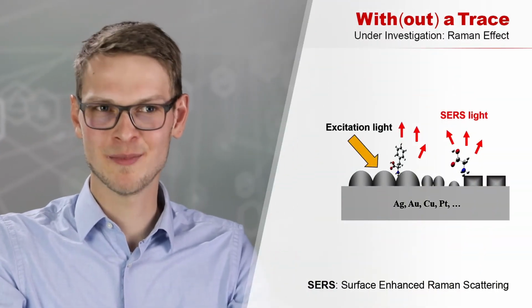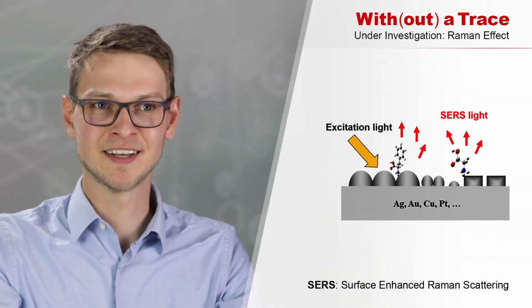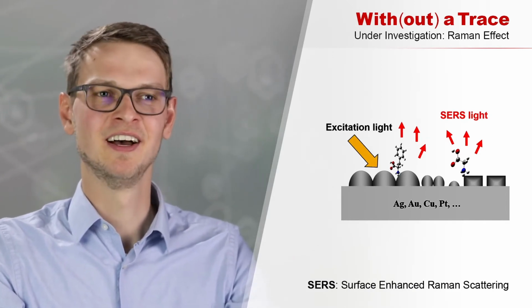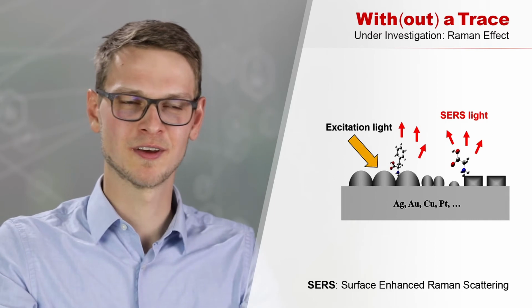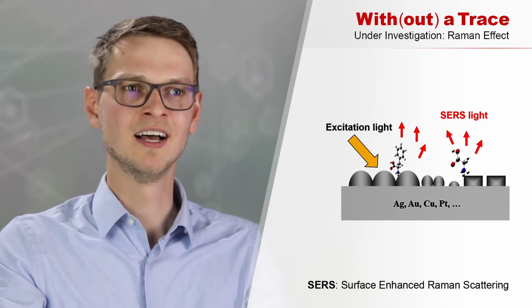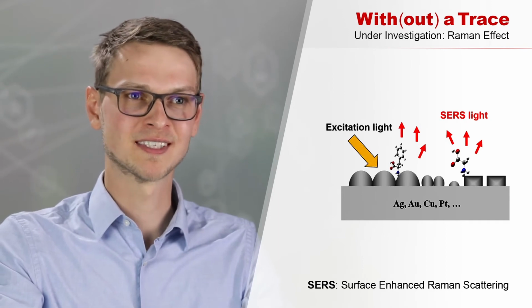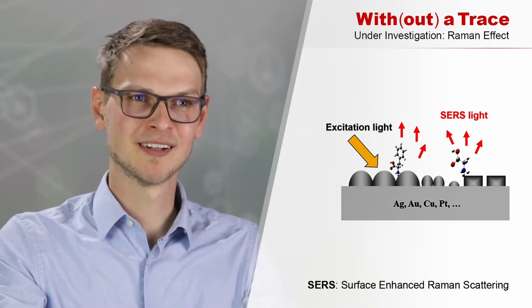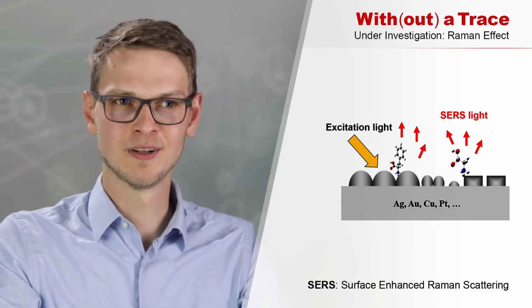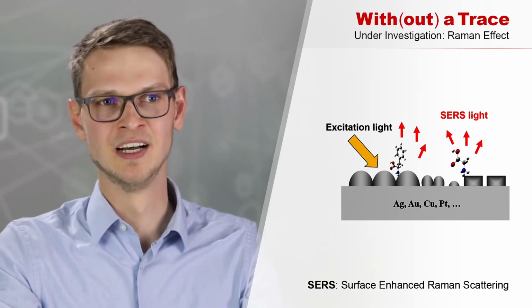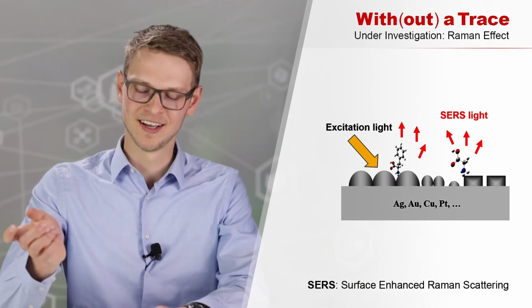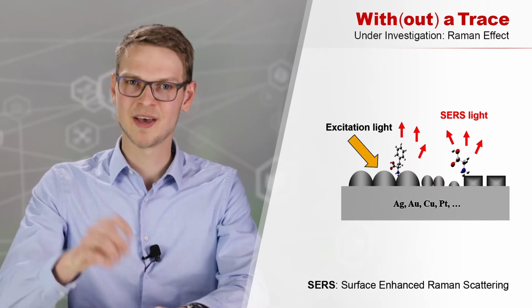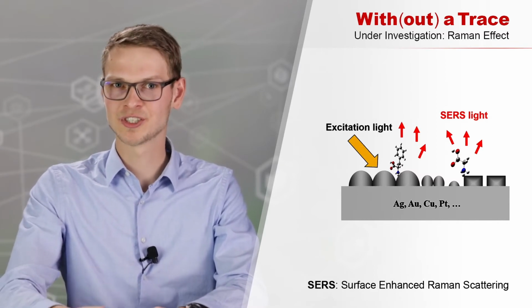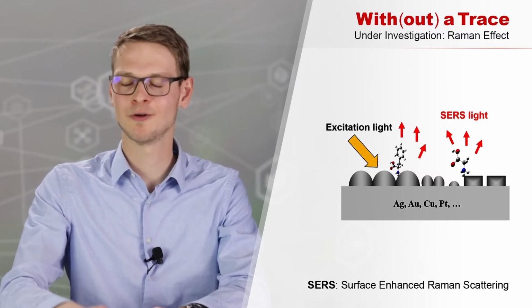In Raman spectroscopy, SERS is the abbreviation for Surface Enhanced Raman Scattering, or Raman Substrate. This technique is an extension to regular Raman spectroscopy if the signal strength acquired with regular Raman spectroscopy is not sufficient. In this case, one employs a substrate which has a metal structure on the substrate. For example, those can be silver or gold nanoparticles. As a consequence, the excitation light will interact with the metal substrate and the sample, which is placed as a solution on the substrate.